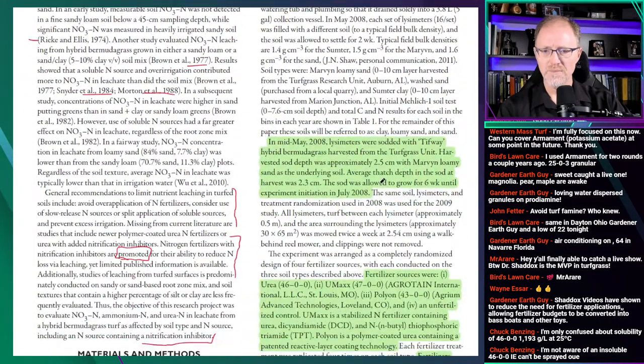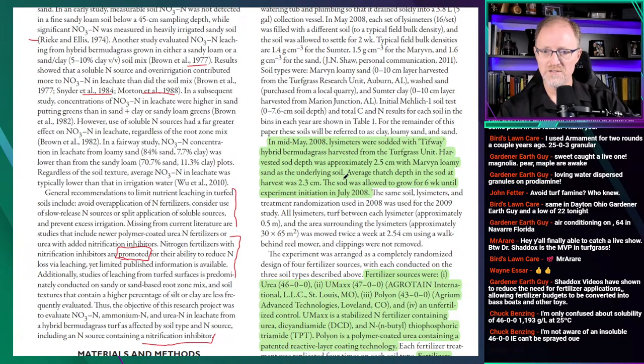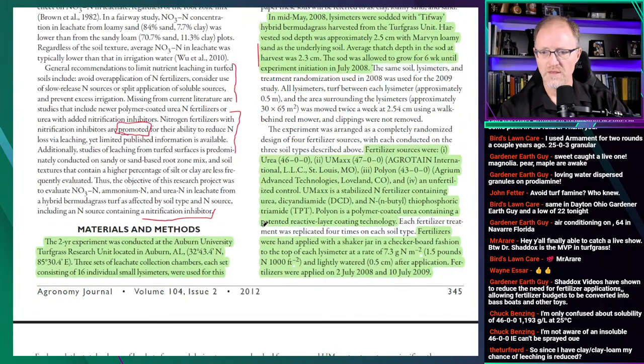Okay. In mid-May 2008, lysimeters were sodded with Tifway hybrid Bermudagrass harvested from the Turfgrass unit. So we're dealing with Tifway 419, guys, in Auburn, Alabama. Harvested sod depth was approximately 1 inch with Marvyn loamy sand as the underlying soil. Average thatch depth in the sod at the harvest was around 1 inch. The sod was allowed to grow for 6 weeks until the experiment initiated in July 2008.